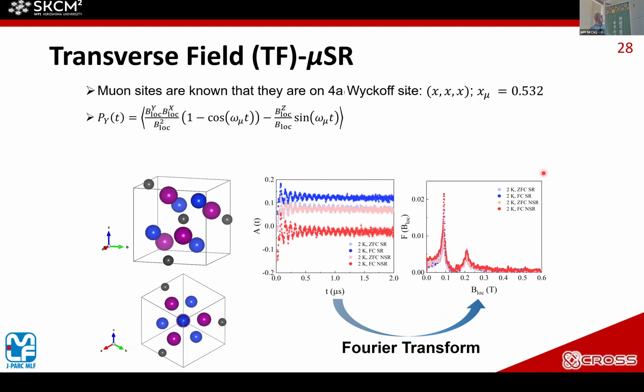This is the typical muSR data obtained at 2 Kelvin. So there are many frequency signals. And when we Fourier transform this time spectra, we can obtain the internal magnetic field distribution. And this peak is coming from the H1 site muons. This muon has a sharp internal field. And the other muons, 3 muons, which are on the same plane, the 111 plane. And these 3 muons have a broad internal field distribution.